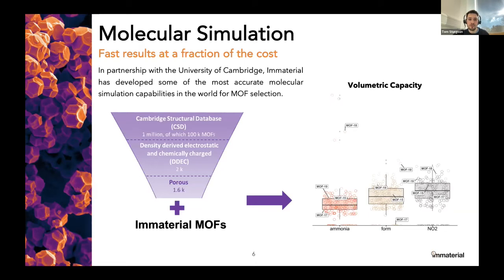in an indoor environment. And then doing those molecular simulations allows us to generate these box plots on the right hand side. So there's a vertical axis not shown precisely here, which is volumetric capacity. And so basically each of these circles is a different metal organic framework that we've simulated, and the higher up it is, the better the performance we'd expect against the three gases that we simulated, so ammonia, formaldehyde, and NO2.